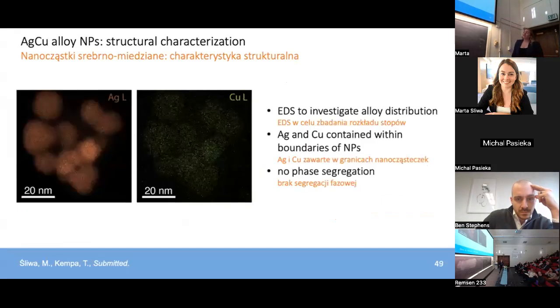So we also confirmed the presence of silver and copper in our particles using EDS spectroscopy, and here we see data for a 2.5% copper alloy sample. We saw that the silver and copper is relatively well contained within the boundaries of the nanoparticles. It might be a little bit hard to see on the screen, but most importantly, we saw that there's no phase segregation or formation of mainly green and mainly orange portions of these nanoparticles within this data.